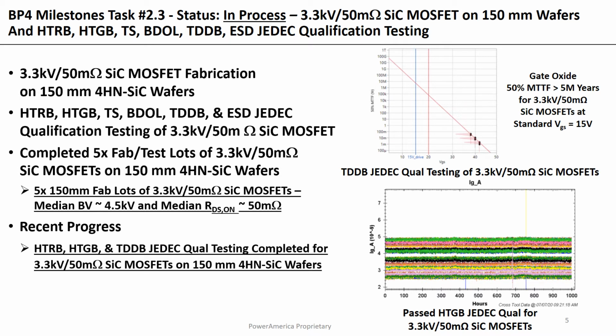If you look in the upper right hand corner, you see the TDDB plot for these 3.3 kV 50 milliohm silicon carbide MOSFETs extrapolated up to the operating gate voltage of 15 volts, which is the operating gate bias for these devices. At that gate bias, you have a mean time to failure of greater than 5 million years, which indicates these are very stable gate oxides in these 3.3 kV silicon carbide MOSFETs.